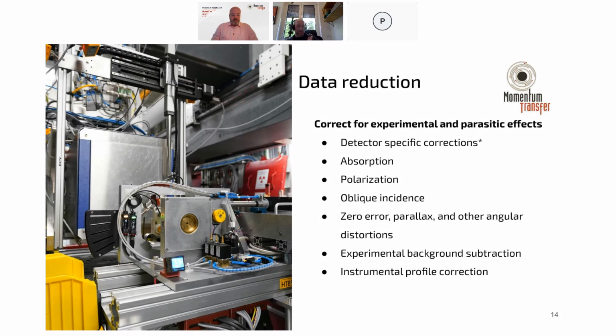In this case, we have a very precise positioning of the sample, and we can correct for any detector-based offset errors, which mostly come from parallax, which is the effect of having a flat detector. And we do this using calibration standards from NIST. And finally, as I said, we subtract the experimental background, and we also correct for the instrumental profile, so the amount of broadening that comes from the measurement apparatus itself rather than the sample.